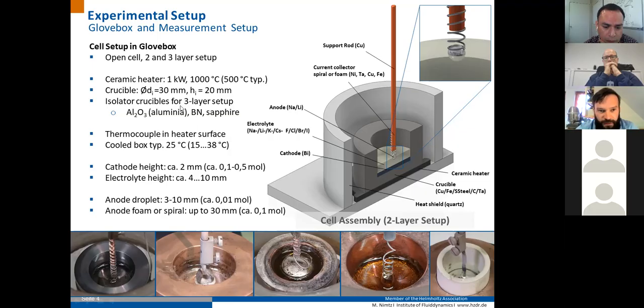There are some 3-layer setups, as I said. There we use alumina or boron nitride or sapphire to insulate the inner diameter of the crucible, and only then it's possible to operate the 3-layer setup where we have 3 fully liquid layers on top of each other. As I said, in the heater surface, there's a thermocouple installed, which is used to regulate the heat output of the ceramic heater. The outside of the box atmosphere is cooled, typically to 25 degrees Celsius. It operates between 15 and 38 degrees Celsius. So we have lots of heat transfer from the hot crucible, from the hot electrodes in the cell to the glove box atmosphere.